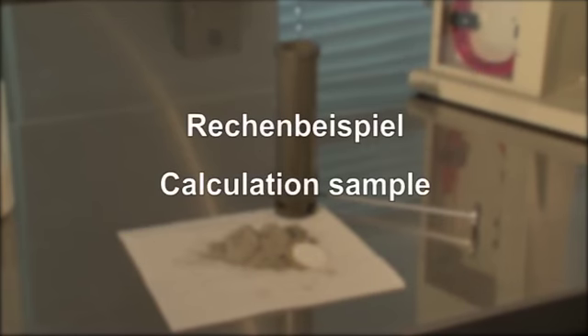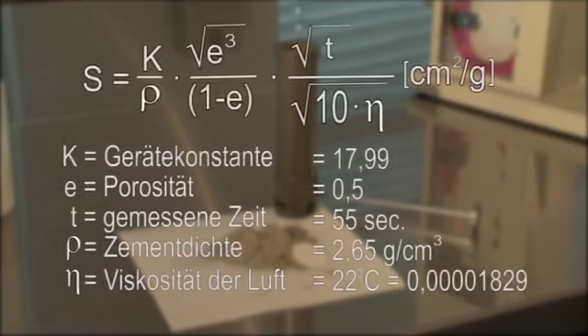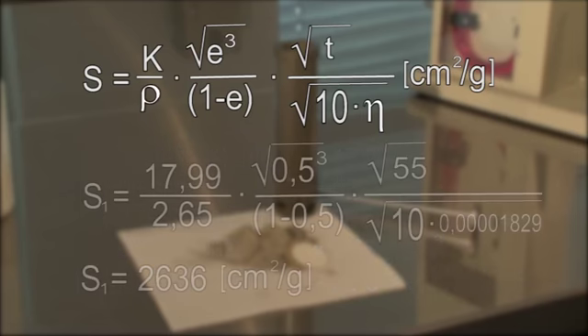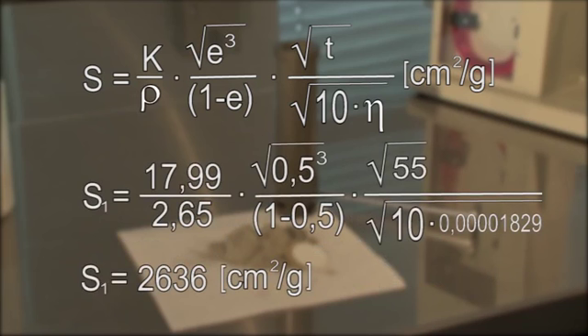A sample calculation. The apparatus constant amounts to 17.99, the porosity 0.5. The time as a mean value amounts to 55 seconds. The density of the cement is 2.65 grams per cubic centimetre. The viscosity of the air is accurately determined to within 1 degree as a mean value at 22 degrees Celsius. The specific surface area S1 of the cement can now be calculated from the mean value of the two measurements.